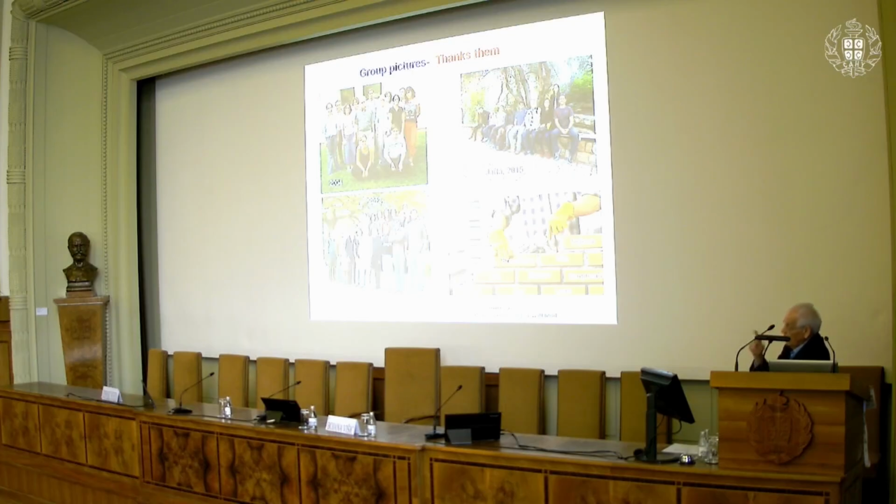But in the case of the electrical measurements with Iwasa, we beautifully showed the Little-Parks oscillation of the Cooper pairs that are going in phase, basically, preserve their phase and interfere with themselves and form, as a function of magnetic field, minima and maxima. So this is a beautiful demonstration of 1D superconducting transition.